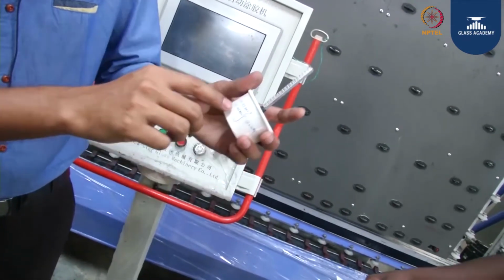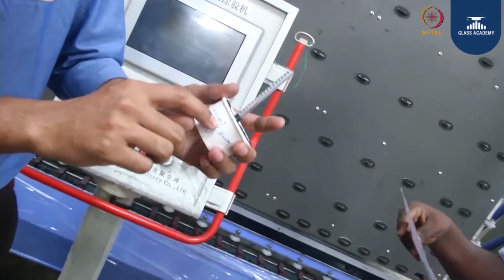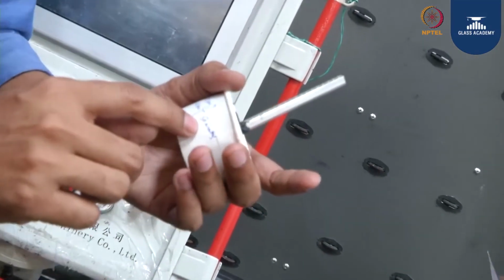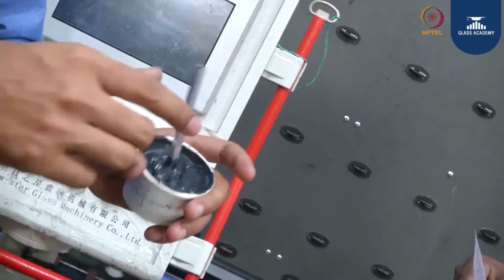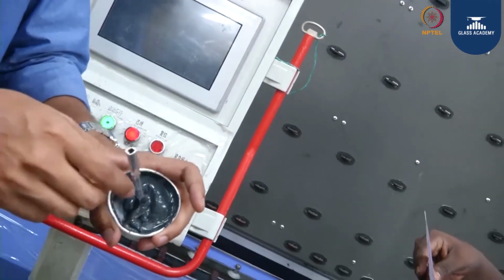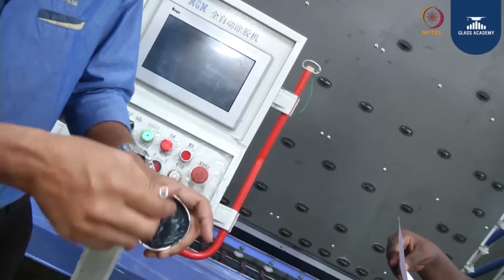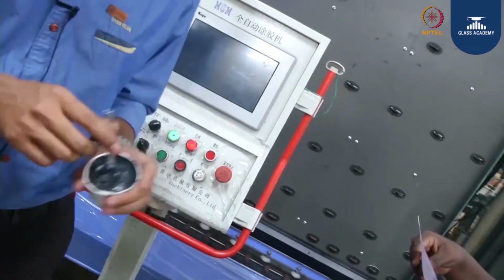That time we need to note down. If you see, the start time for this spacer is 9:55 and the end time is 10:45, so the snap time is known as 50 minutes. At that particular 50 minutes, the silicone got cured. That is known as snap time.